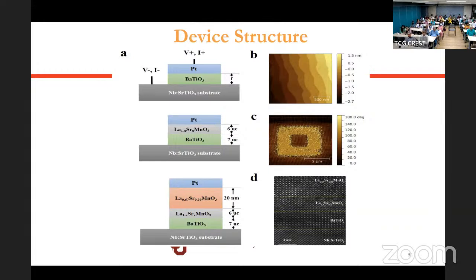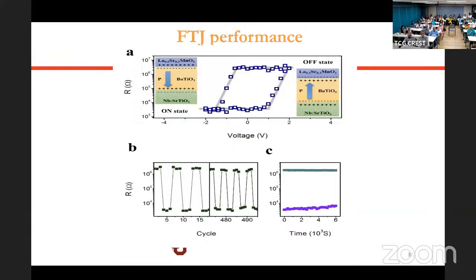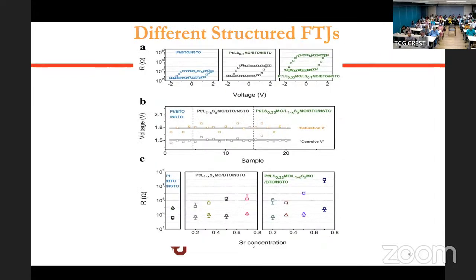Now if I look at these three classes: this is the simplest ferroelectric tunnel junction, this one has one extra layer, and this one has two extra layers. So what happens? When you look at a typical ferroelectric junction, you see almost three orders of magnitude change in the resistive values in the switching. But now when I make a comparison between these three different cases, what you notice is that the switching voltage is the same in all three cases. This is a 1.5 volt switching, and 1.8 is the saturation voltage. It doesn't matter what layers I have in these three devices.